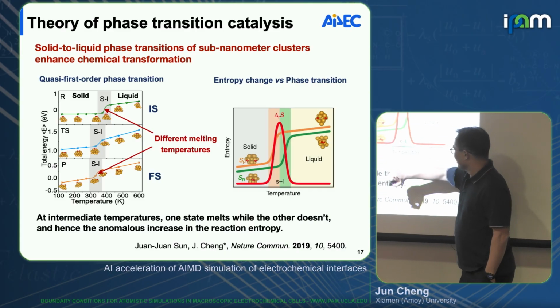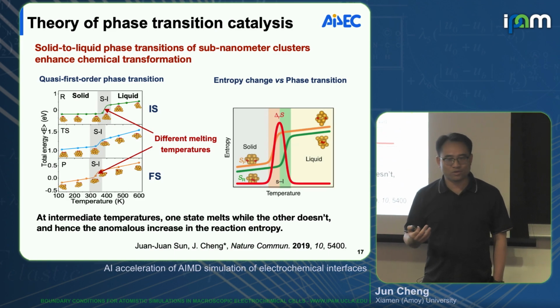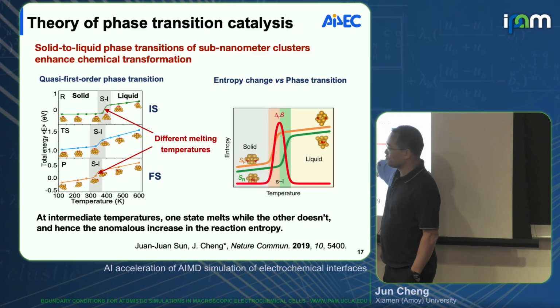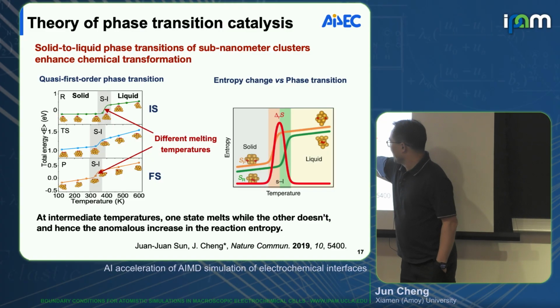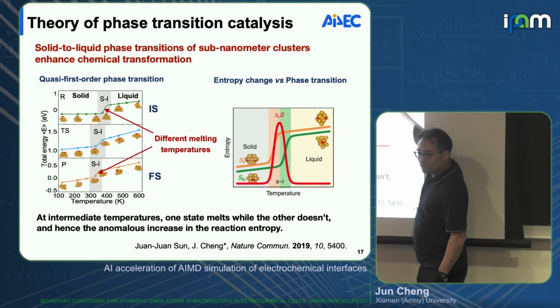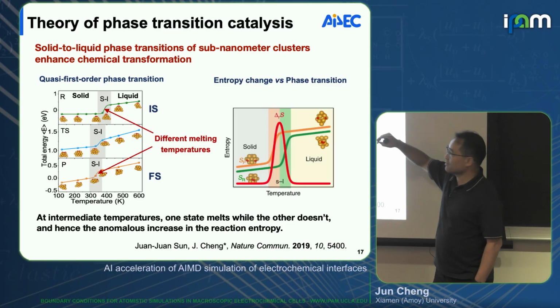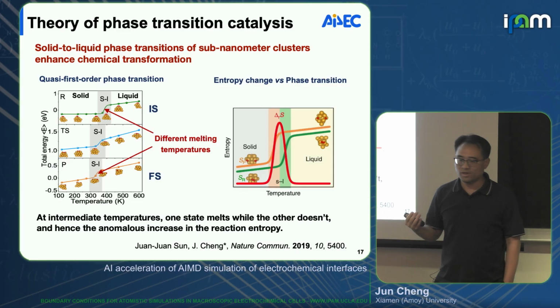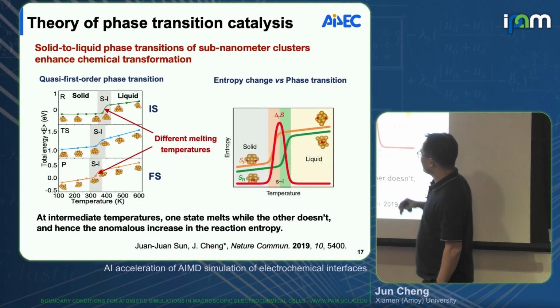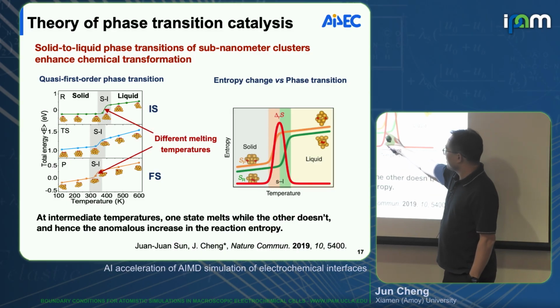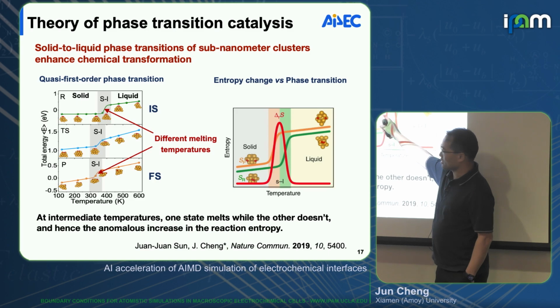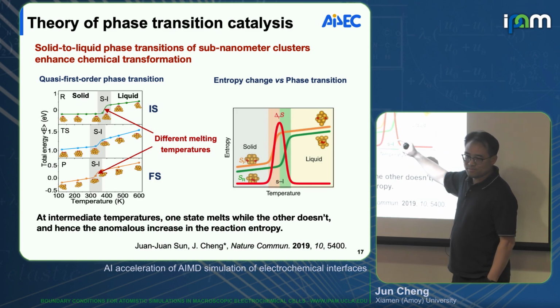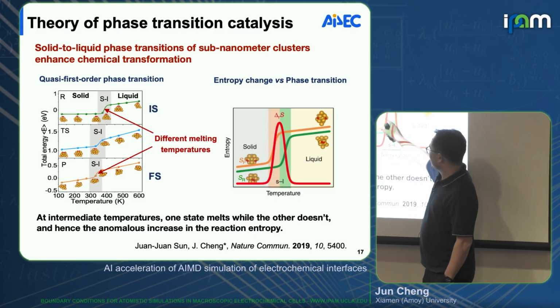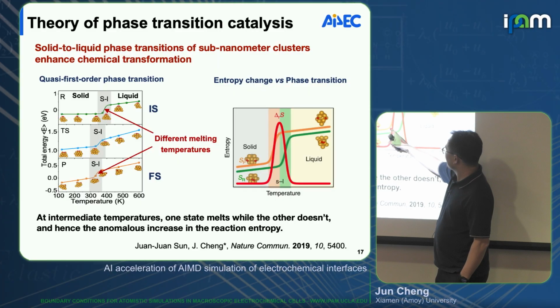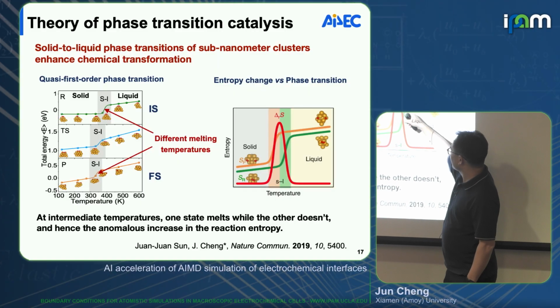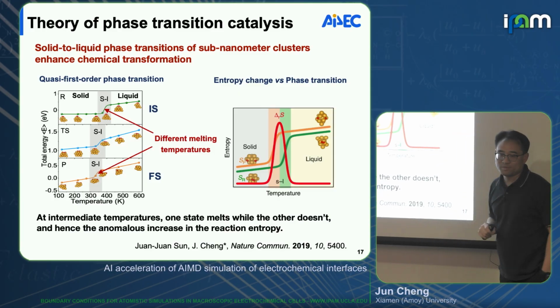At low temperature, both reactant and product are more solid state-like. They have very low entropy, but their reaction entropy, delta S, is very small. At a high temperature, both states will eventually melt. Both states are liquid-like. They have high entropy, but their difference, again, is small. What is interesting is in this intermediate temperature range, the reactant is still solid state-like, but the product starts to melt because you have a mismatch in the melting temperature between the two states. Then the reaction entropy will start to increase because the product starts to melt. And when you increase the temperature and the reactant starts to melt, the reaction entropy, delta S, also